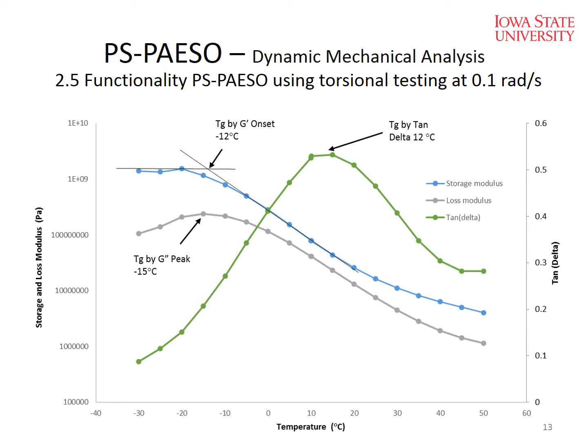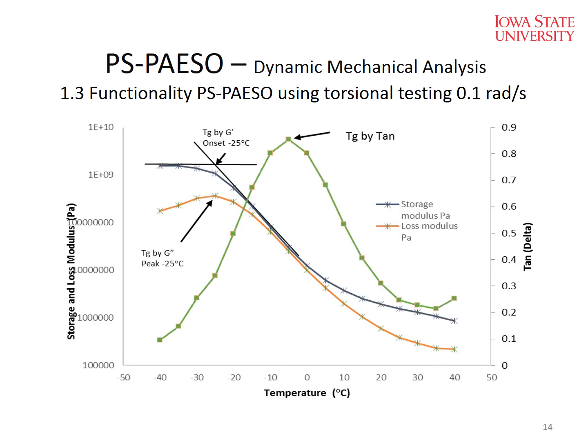This just shows you doing some DMA work where we get our glass transition temperature. This is again a 2.5 functionality. And it just highlights that we're about minus 12 centigrade. Okay? We go to the 1.3 functionality, we drop it down to minus 25. We can drop it down to, like I mentioned before, to 1.1, and we're about minus 32. Okay? So that's pretty impressive.